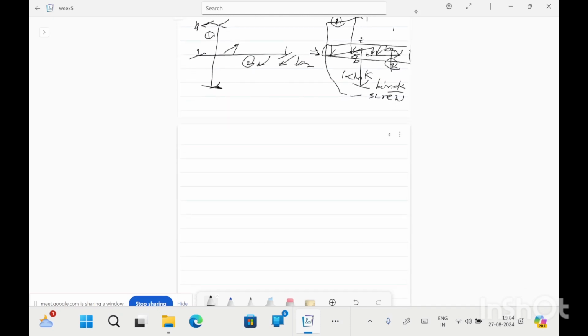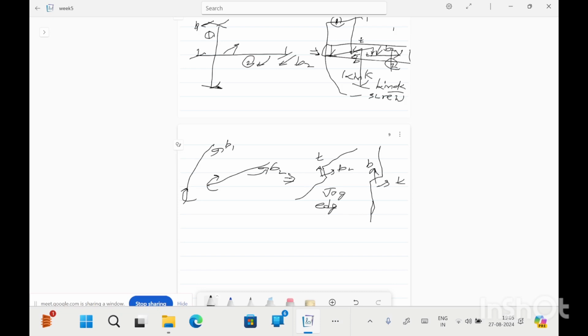While in the case of screw dislocations, if two screw dislocations are intersecting, B1 and B2, after the intersection a step out of the slip plane is formed for the screw dislocations. So this is B2 and this is the line vector. Similarly, this is B1 and this is the line vector. So these formed are jogs of edge character, because the Burgers vector and line vector are perpendicular to each other in this case.